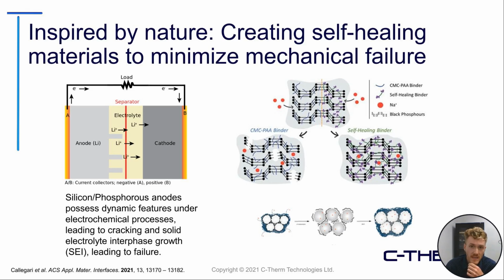Now, what this group did is they took inspiration from nature, using these newly synthesized hydrogen bonding type materials to encapsulate some of the anode and create a barrier so that it is able to self-heal and prevent this growth from occurring from one side of the anode to the other.